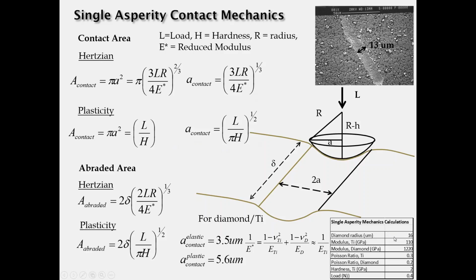When we utilize values for the diamond stylus, the modulus of titanium, and all of the other parameters here, we calculate that radius to be about 5.5 microns, which is really pretty close to the 12 or 13 microns that we're measuring directly from the measurement. And so it looks like single asperity-wise, we can use these concepts of contact mechanics and hard-on-hard contact mechanics to